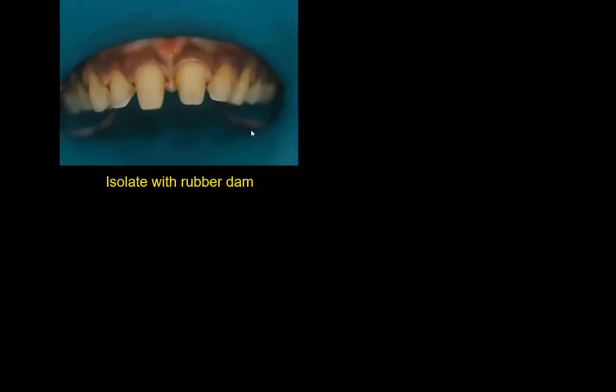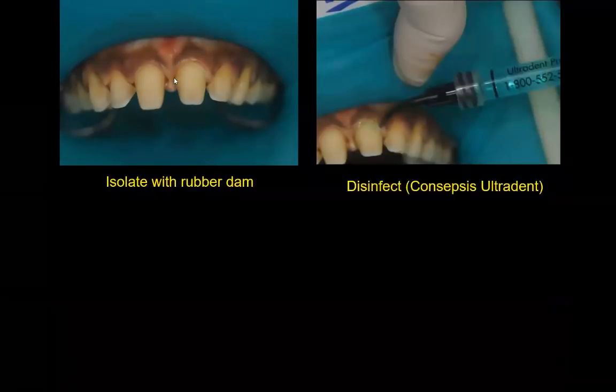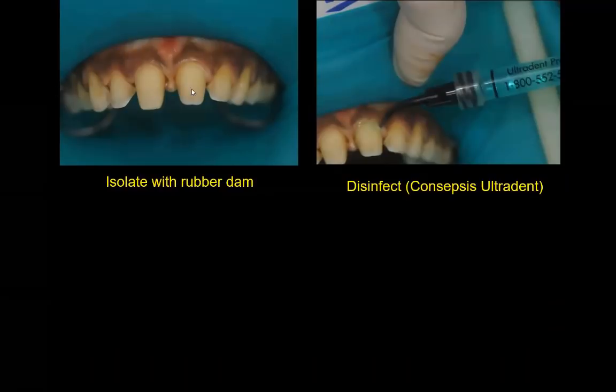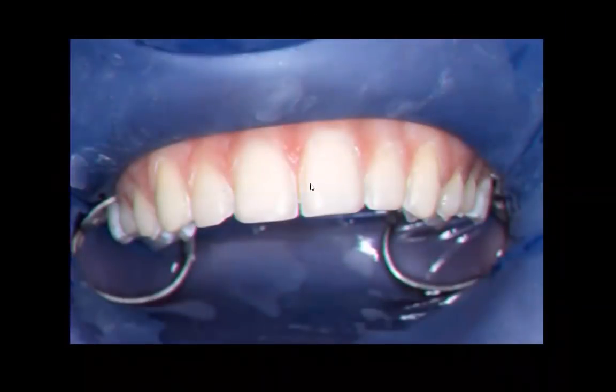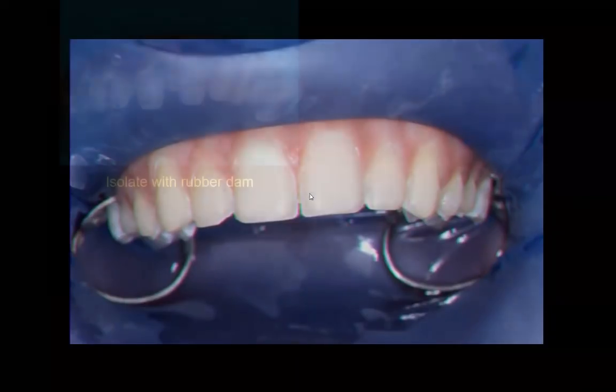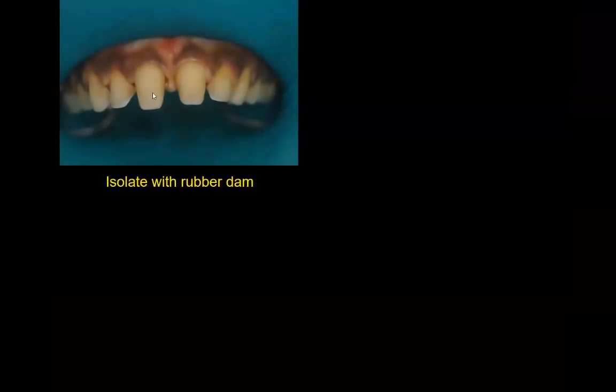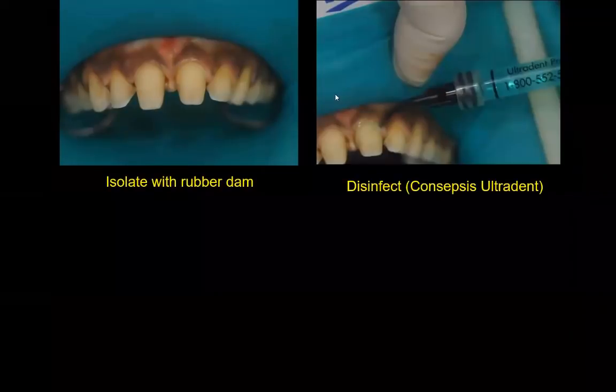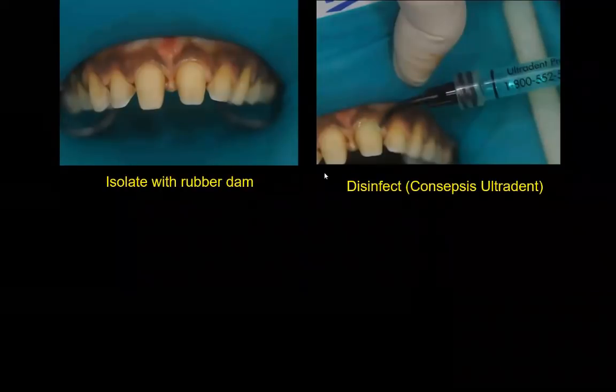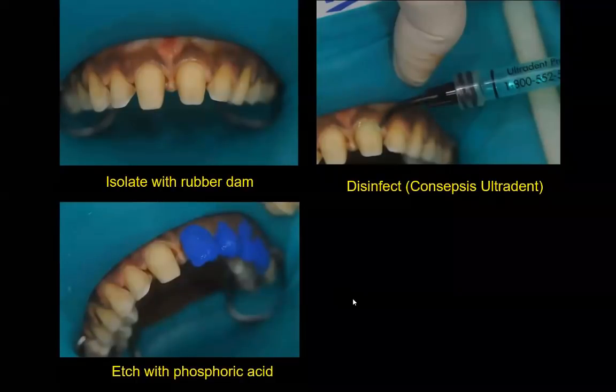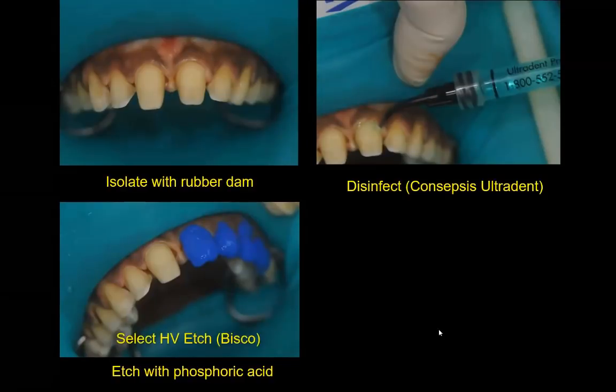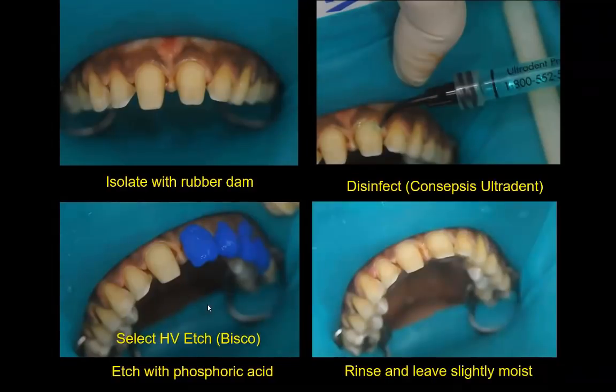So here's our case. We've isolated with a rubber dam. So this is something where, because of decay, interproximal restorations, whatever, we've broken contacts. A lot of times in this case, I don't like to break contacts, and I won't unless I have to. In the case we're showing here, we have broken contacts, so there is dentin exposed. It's mostly enamel, but there is some dentin, but we're still going to use the total etch technique. This is Consepsis, where we're doing our rinse, and we're disinfecting. Here we've etched 5 teeth and we rinse. This is Bisco Select HV Etch.